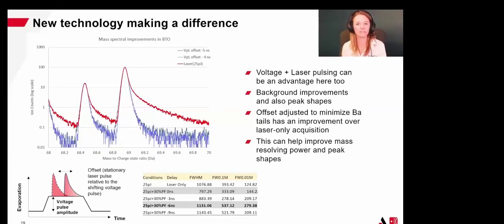But one thing that we can see here is as we continue to analyze our mass resolving power closer to the bottom of our mass spectrum, so these are the full width tenth and hundredth max, we see much larger improvements in mass resolving power. So our peaks are getting really sharp at the noise floor of the data. And if we can reduce that background of our peak and improve our mass resolving power, that's going to give us better data quality and help us to find those low concentration elements. So voltage plus laser is something worth considering if you're analyzing MLCC materials.